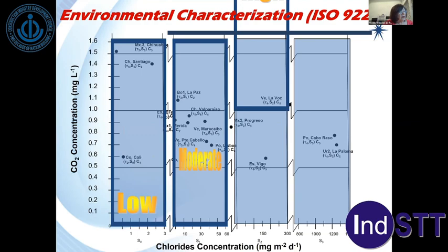where the chloride ion content in the atmosphere is one of the most important factors to consider, but also in urban and rural environments, where CO2 content is one of the important factors causing carbonation of concrete, and therefore corrosion of the steel reinforcement. It is important to highlight that up to date, no regulation has been defined to characterize the exposure environment for reinforced concrete structures. So the ISO norms for metallic materials were used.